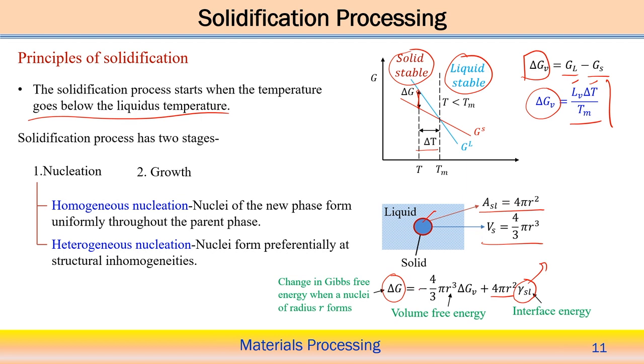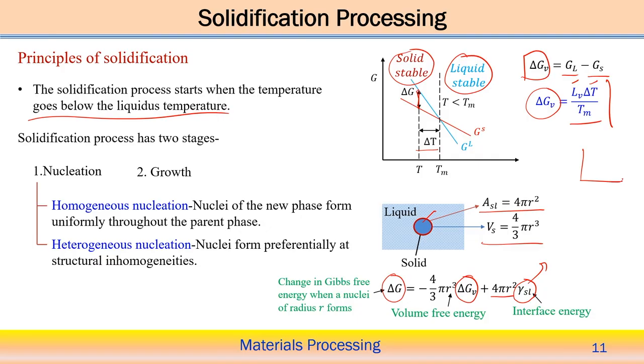But in the Gibbs free energy, we have written a negative sign with 4 by 3 pi r cubed, and delta Gv is the free energy per unit volume, while 4 by 3 pi r cubed is the total volume of the particle. We have already seen that the Gibbs free energy curve is gradually decreasing as nucleation occurs. That's why I put a negative sign for the volume free energy available. But in the other case, since a new interface forms, it will consume energy, so the surface energy term is on the positive side.